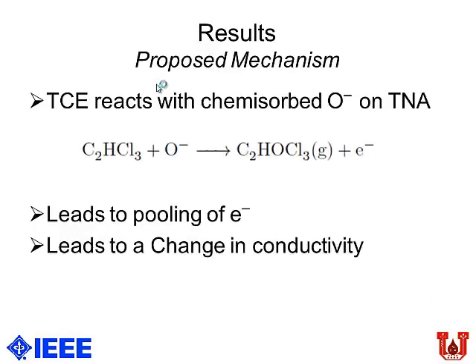So trichloroethylene reacts with O- ions. So basically your titanium nanotubes have chemisorbed oxygen on it. Basically oxygen gets absorbed on the substrate and O- ions are present. So your TCE reacts with these O- ions and you get electrons being formed, an excess of electrons. So the pooling of electrons would lead to a change in conductivity. You get a higher current when TCE is passed.